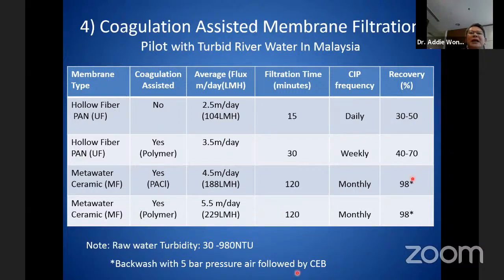CEB means chemical enhanced backwash. It's the same backwash, but this backwash water has some chlorine, sometimes some sulfuric acid. So it will further clean the membrane with less water, instead of many backwashes. When we changed the coagulant to polymer, we found that actually the flux can go even higher with the same conditions. So this is the result we have conducted in Malaysia.